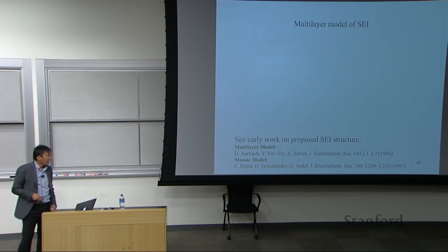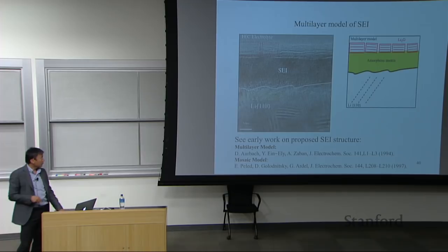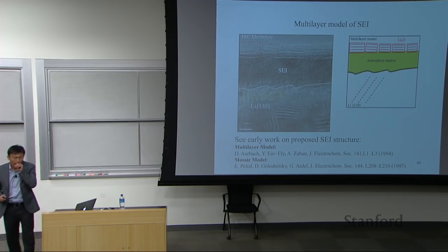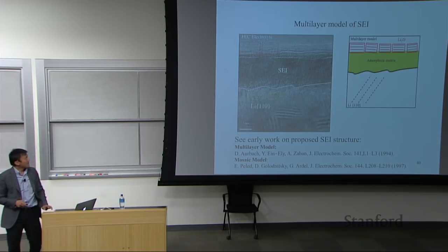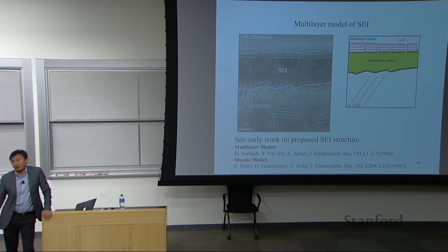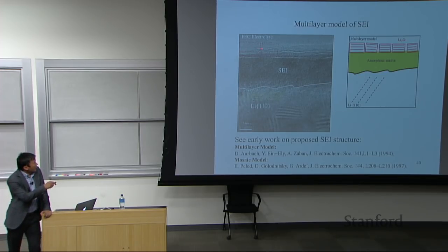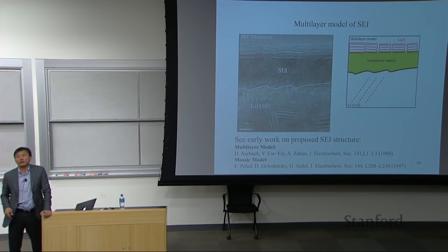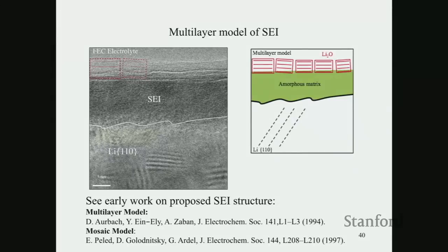However, we have also seen, by adding the additive, so-called FEC, into the electrolyte, we can see the multi-layer structure of SEI as well. In this case, it's inorganic lithium oxide on top of the amorphous matrix of this polymer.